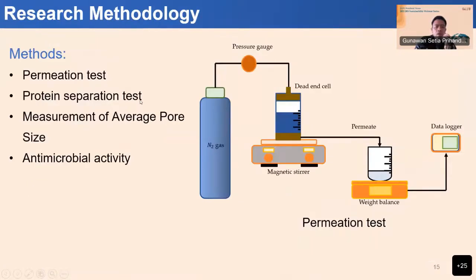Okay. And then in order to test whether the membrane is good enough for water or air filtration purposes, we use different types of tests. What we call here a permeation test involves pushing nitrogen gas into the dead end cell here. We have the pressure gauge here, which we set at 2 bar for the pressure into the dead end cell, and then we place the membrane on the bottom of the cell, and then the nitrogen gas will push the water out of the cell, and then we will have the permeate here.